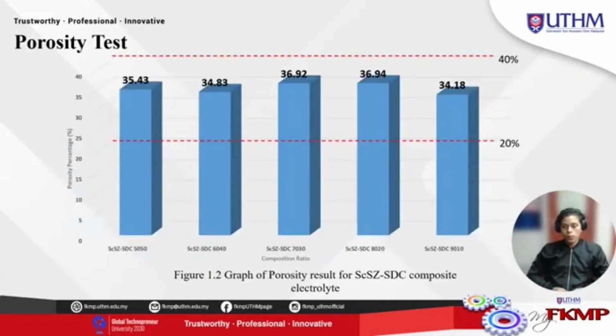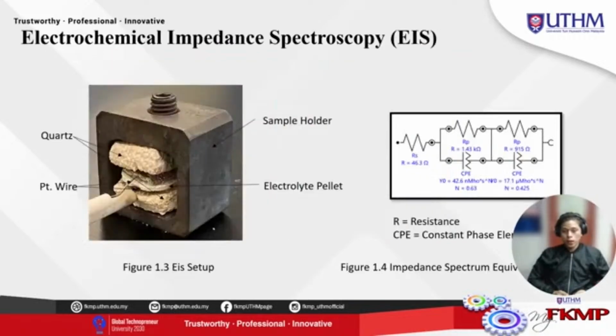Okay, next is the porosity test. The results show percentages between 20 to 40. 20 to 40 is the requirement of the cathode porosity. The reason we take the cathode requirement is because the electrolyte will be combined with the cathode for the transportation of ion. The best porosity is 80-20, which is the highest one, 36.94%.